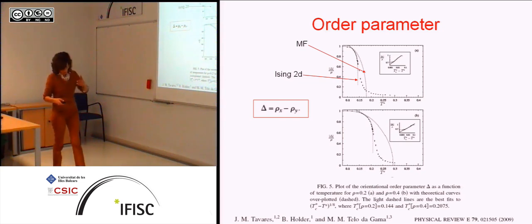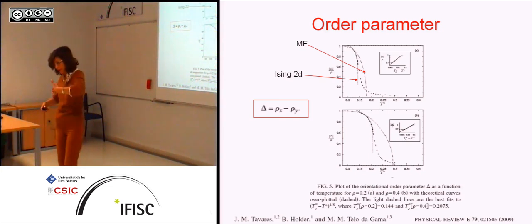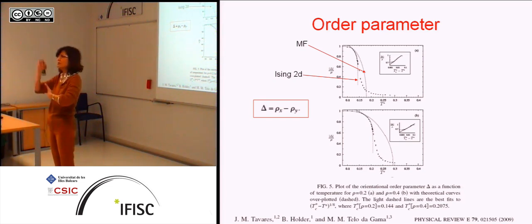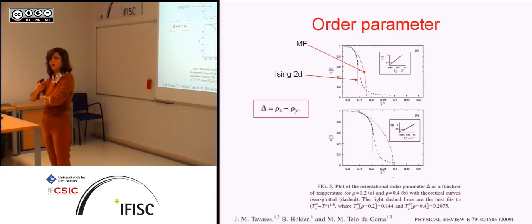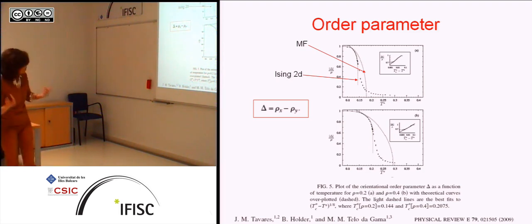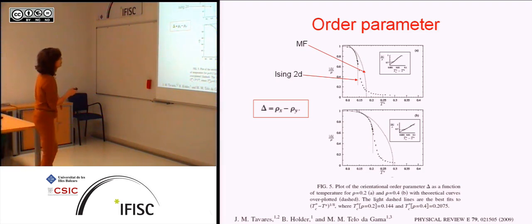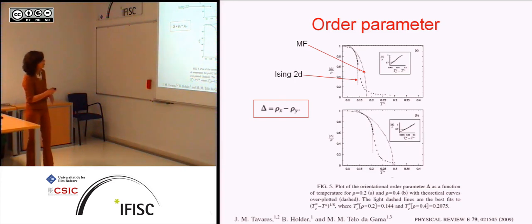We calculate the order parameter. The order parameter here is really the number of monomers or bonds you have in one direction minus the number of bonds you have in the other one. So if you're above the transition, this is 0 on average, and if you're below the transition, this is different from 0, and it goes to 1 at 0 temperature. So this is the proper order parameter, and we have done this for two systems at two different densities. This is low density 0.2, and this is the high density. This is the order parameter as a function of temperature, and you see the typical sigmoidal curve, continuous transition.